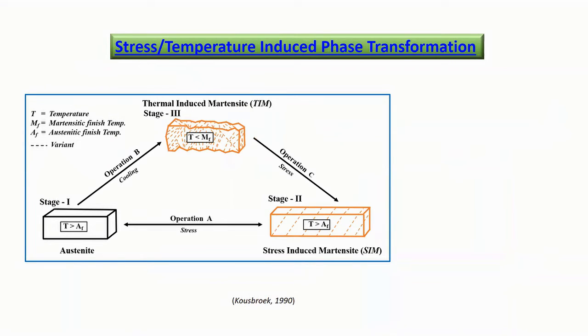Okay, now, as I said, this can happen in two ways, either with the application of stress or with the application of temperature. So just thought of showing you how this can happen. So initially, if we are at a temperature higher than the austenite finish temperature, means that if we are applying stress, these austenite grains have no other way to deform other than by converting to martensite, right?